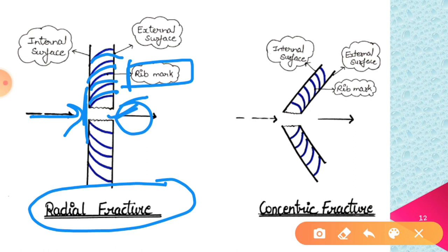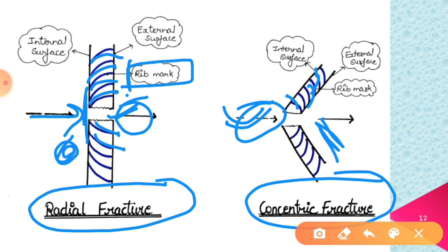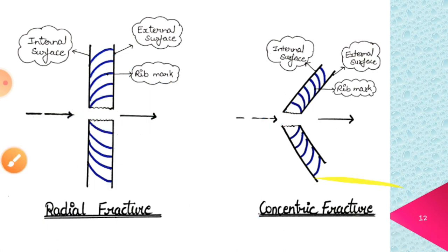The point of impact side is the surface of impact, and the just-opposite surface breaks first in radial fractures — that opposite surface bears perpendicular rib marks, and the surface of impact bears a tangent rib mark. In concentric fracture, the side of impact breaks first, so that side bears perpendicular rib marks, and the opposite side bears tangent rib marks. In other words, in radial fractures the rib marks on the external surface are perpendicular, or at right angle, to that external surface.